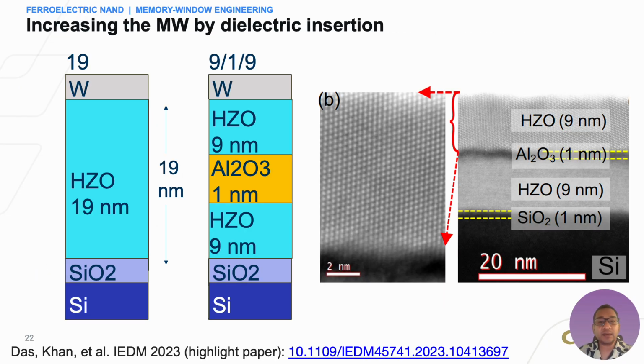The first memory window experiment compares a uniform 19 nanometer HZO film with a laminated 9-1-9 stack: 9 nanometers of ferroelectric hafnium zirconium oxide, 1 nanometer of aluminum oxide, and 9 nanometers of ferroelectric hafnium zirconium oxide. The total thickness remains 19 nanometers, so the comparison isolates the dielectric insertion rather than simply adding a material. The microscopy on the right verifies the thin aluminum oxide layer between the two ferroelectric regions and the interfacial oxide at the silicon.